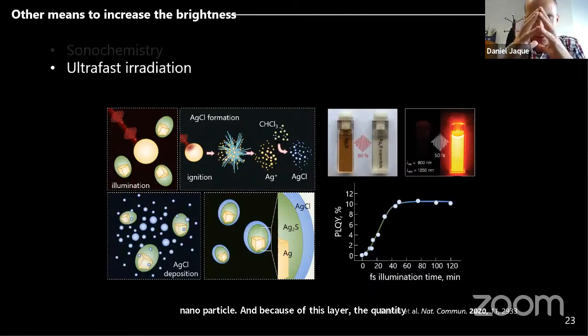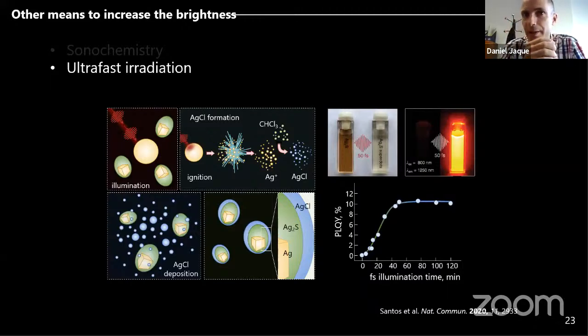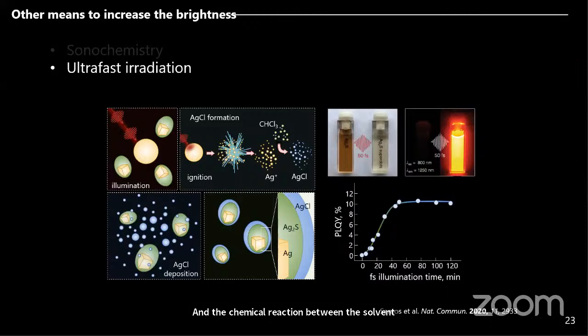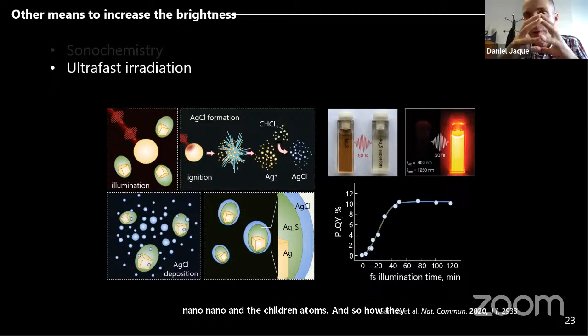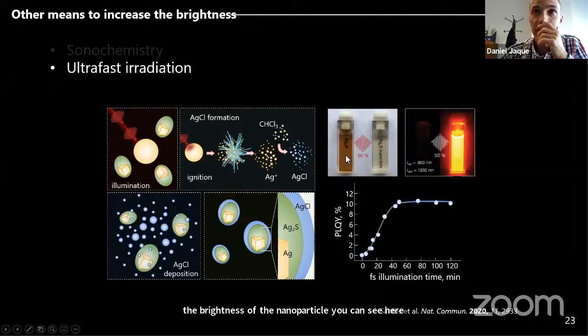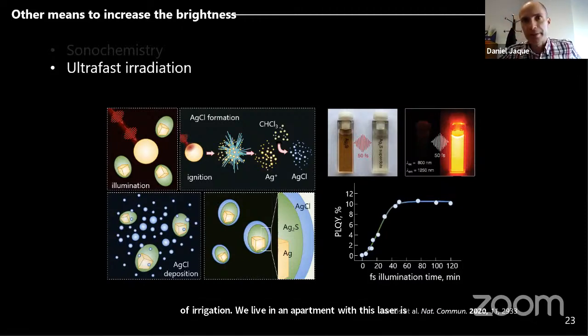So the idea is you have your nanoparticles, you irradiate them with an ultra-fast laser, and this ultra-fast laser starts a chemical reaction between the solvent and the silver atoms and so on, and they create a protective layer surrounding the nanoparticle, okay? And because of this protective layer, we increase the brightness of the nanoparticle. You can see here, this is the infrared image of the nanoparticles. This is before and after irradiation. You can see that the color changed a lot. You can see here that the nanoparticles become much brighter. Indeed, the quantum yield that we obtain after 40 minutes of irradiation with this laser is close to 10%.